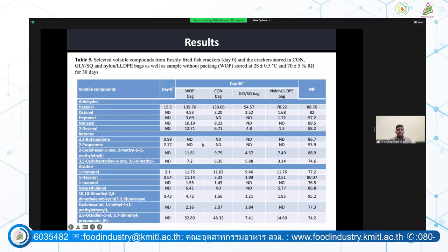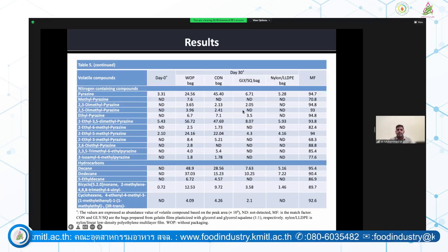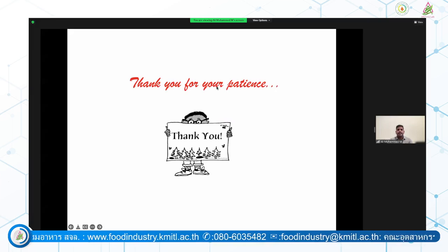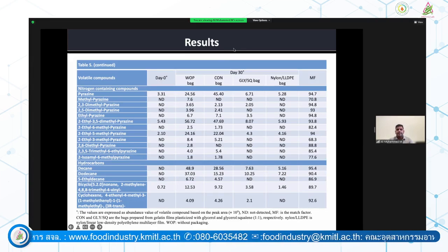And when we also determined the volatile compounds, the primary oxidation compounds, we found lower oxidation compounds present in the nylon as well as in the squalene incorporated bags. And this is the second group of compounds, as we can see, there are several compounds present at not detectable level, and in control and the gelatin stored bags, they are still present at significant level. So this was the overall presentation indicating the effectiveness of squalene incorporated and ultrasound assisted extracted compounds.